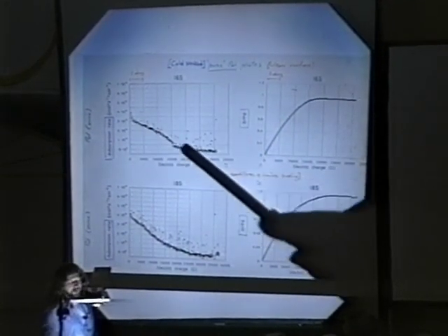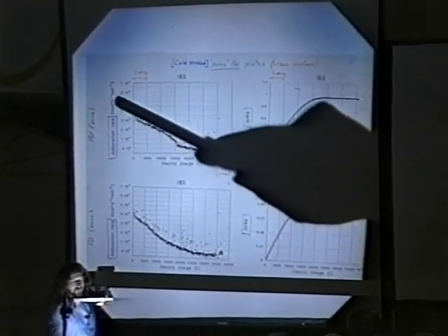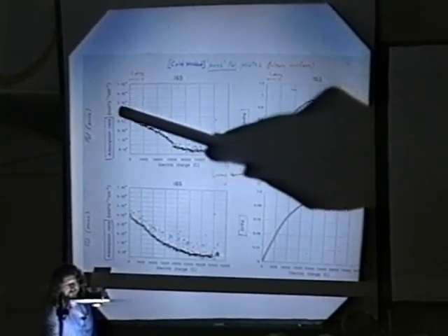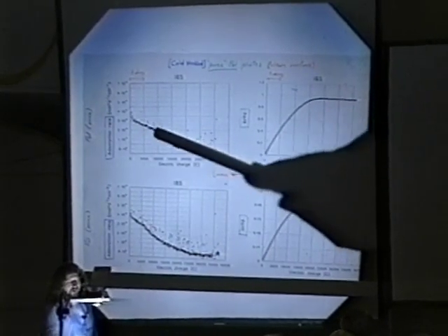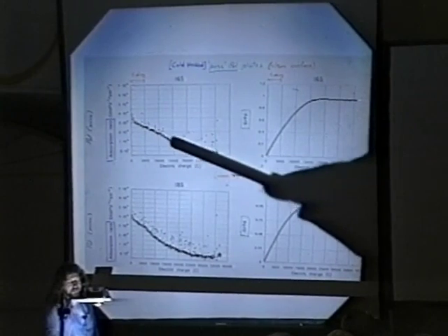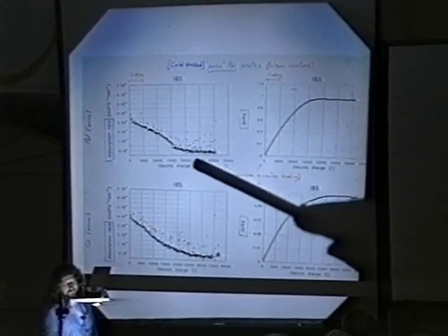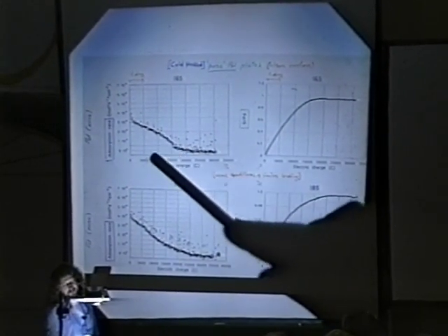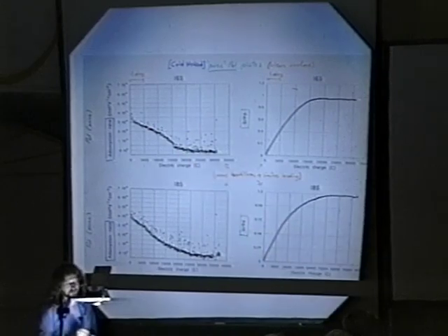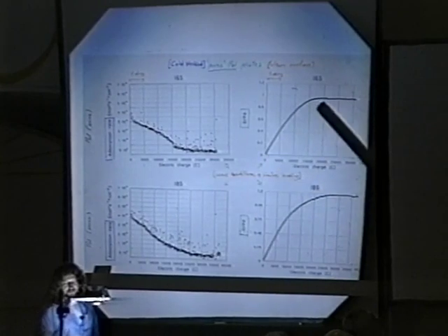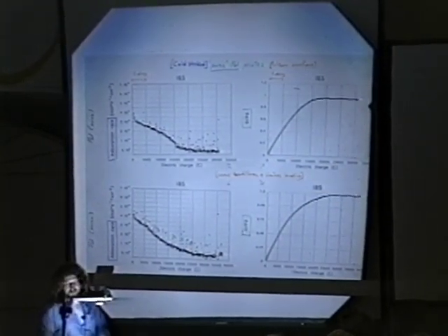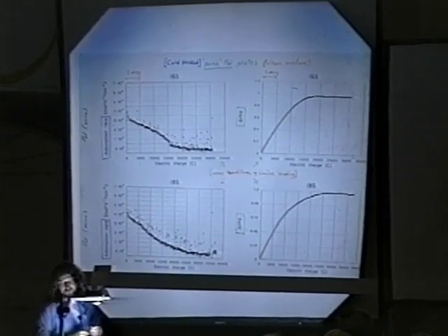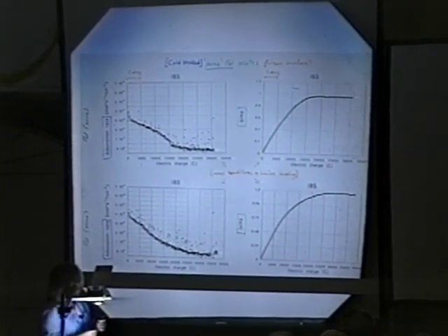This is the absorption rate, normalized to the surface and time. And this is the typical shape of absorption, very high at the beginning and going to 0 in time. After something like three days, all the deuterium is inside. And this is the deuterium over palladium ratio, and this ratio reaches around 1.